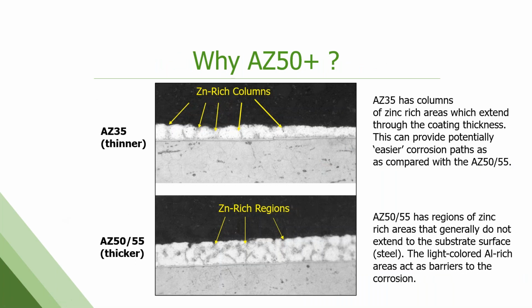So this picture talks a little bit about why that lower coating weight, the AZ35, can be an issue. And again, this is a cross section at the molecular level. What happens when you get down this thin with this coating is the zinc columns can actually reach all the way down to the base steel, which is going to be problematic once they corrode away. Now you have a direct tunnel or line into the base steel, which is going to cause red rust. Whereas on the thicker coatings, very few of those zinc areas make it down to the base steel. You have a lot more aluminum around here to protect that base steel, which is why it's recommended.